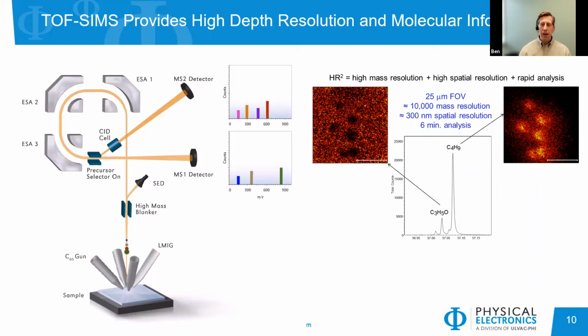So if we have a mass to charge value that we're trying to understand better, we can pick it off and actually send it through a second collision cell so it can be fragmented again to give us better understanding and a better unambiguous characterization of that particular material. And you see here in the image, what we will get is a mass spectrum, and we could then map out different species to show where they are. And with TOF-SIMS, we're getting a little more molecular information.